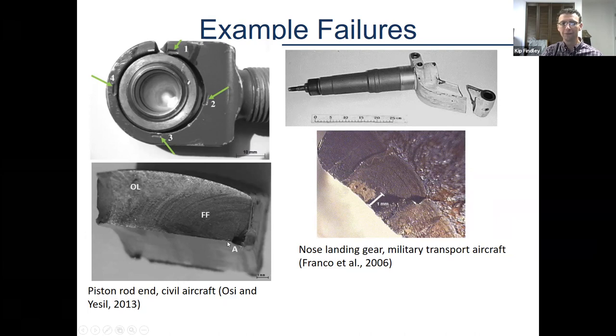So landing gear failures are often associated with fatigue, just like we talked about with the engine, just a different part of the machine. We started off talking about how around 60% of aircraft failures are due to fatigue. We've already seen two pretty good examples of that. The one on the right is from a Brazilian military aircraft. It's a nose landing gear failure. And again, if you look at the fracture surface, you see these markings that are again called beach marks and a really flat fracture, and that's an indication of fatigue.